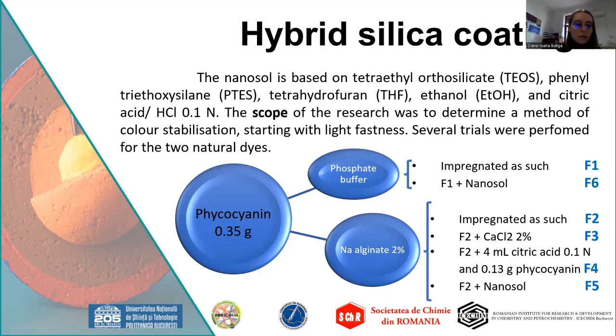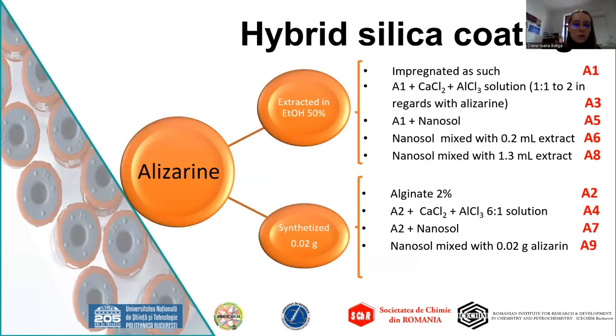Regarding light fastness, several solutions were prepared and used to dye a cotton blend fabric. As seen here, the textile was colored either from the natural dye dissolved in one of the two solvents or with a stabilizing agent that was used to do a second layer over the already dyed cotton blend. A similar approach was used for alizarin, but the two starting points here were of either natural extraction or of synthetic origin.